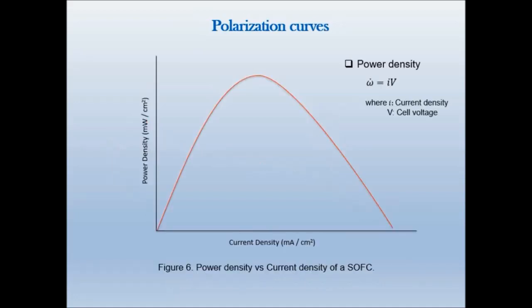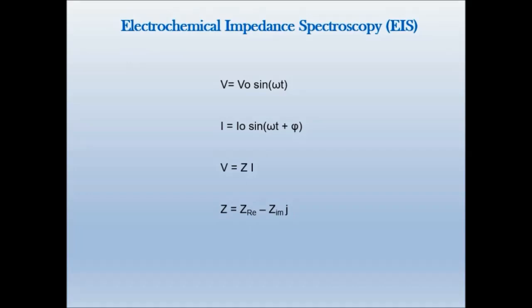From the cell voltage versus the current density plot, the power density is estimated as the product of the current density times the cell voltage. Now, regarding electrochemical impedance spectroscopy, in this technique, a sinusoidal voltage signal is applied to the sample, and as a result, a sinusoidal current signal is measured. The frequency of the voltage signal is varied, and the impedance is the parameter that relates the voltage and the current in this form.